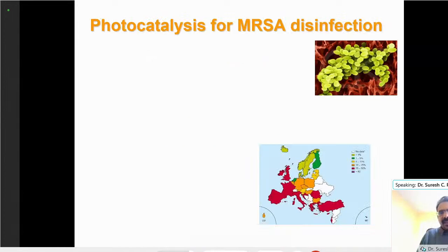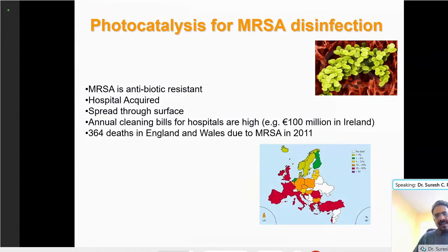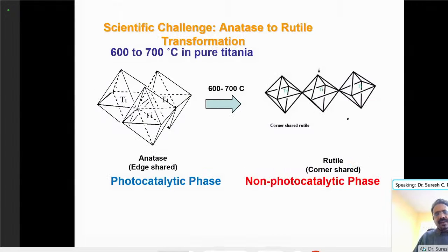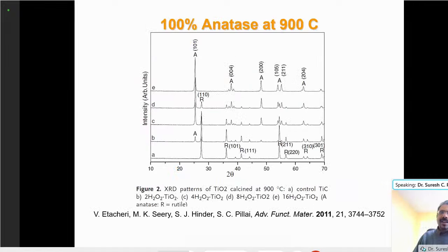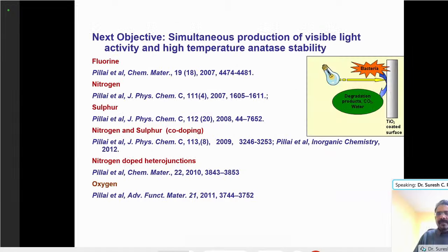I'm going to skip this. So this is what is happening: a photocatalytic phase, which is anatase. When you heat it at 600 to 700 degrees Celsius, a non-photocatalytic phase, which is rutile, is formed. So we have to find techniques and technologies, or come up with protocols, to develop two things. One is high temperature stability and visible light activity. So we did a lot of work.